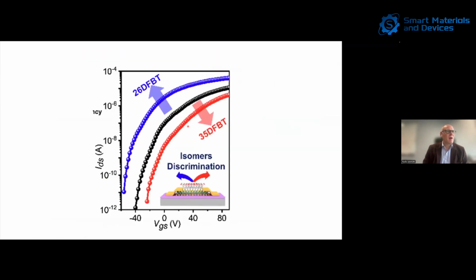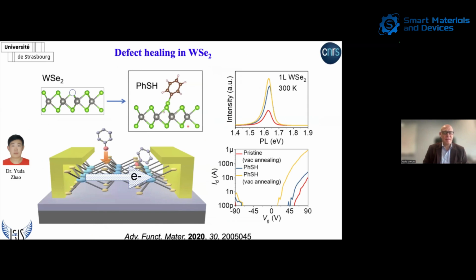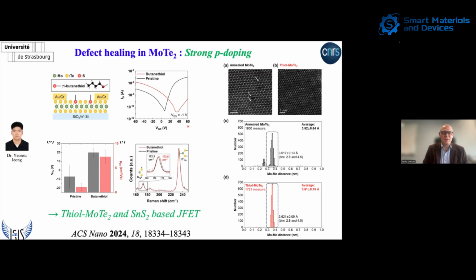Now, I want to stress that this approach of thiol healing is pretty generally applicable. It works also with tungsten diselenide, so you can heal selenium vacancies with a thiol molecule. I'm not going to go into the details of it. You cannot use selenol because selenols are very unstable molecules. And we recently showed that you can also use this to heal tellurium vacancies.